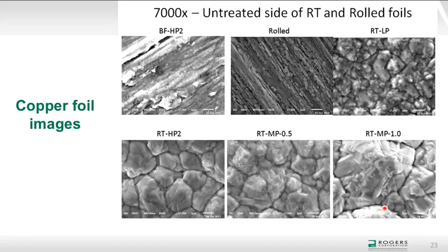And you can see now, instead of seeing lots of small nodules, what you see is kind of a long-range periodicity of treeless mountains. And as we'll discover in the data going forward, it's the short-range periodicity of something like the nodules that affects the insertion loss and the propagation, and not this long-range periodicity of bare mountains.